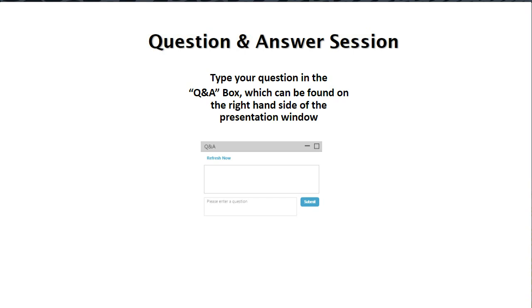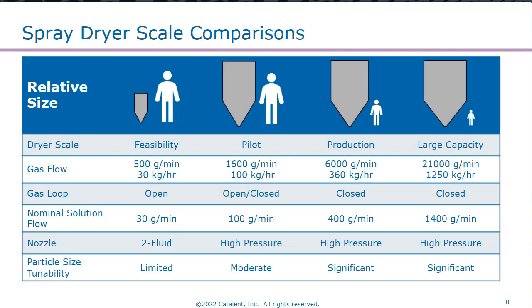Yeah, that's a great question. I'll flip back to our slide on the spray dryer scale comparisons. At the lab scale, we're typically using these small chamber dryers with two-fluid nozzles, and this really limits us to slightly smaller particle sizes than we typically want for downstream flowability. As we switch into the pilot scale with the increased chamber size and a high-pressure nozzle, we're able to increase that particle size into the target range.